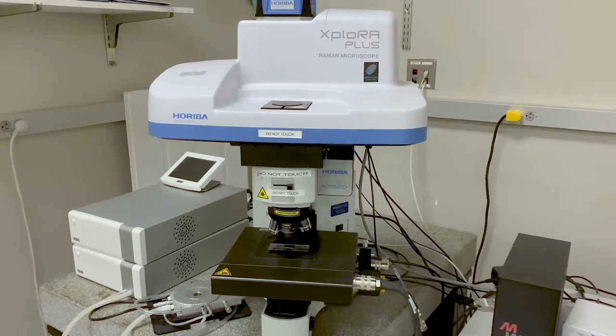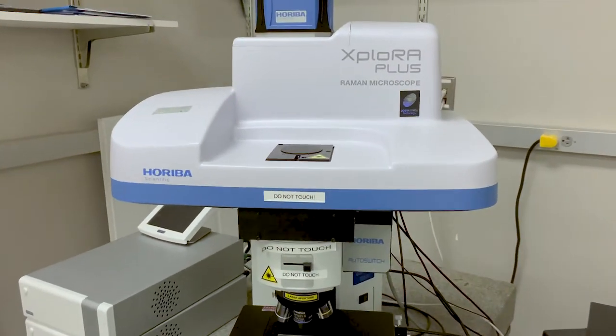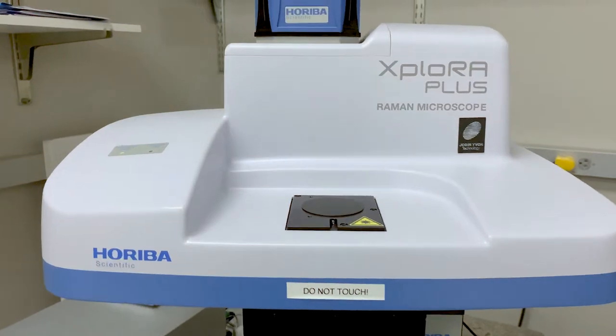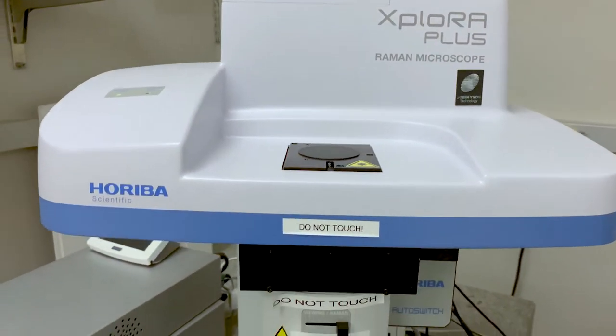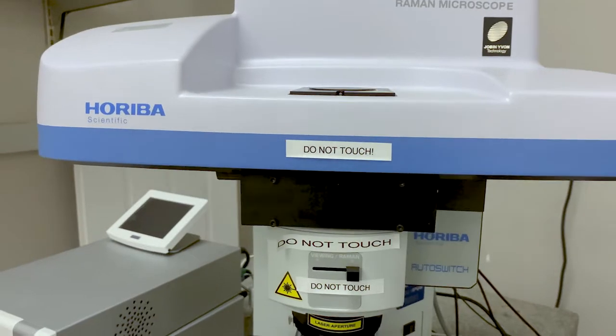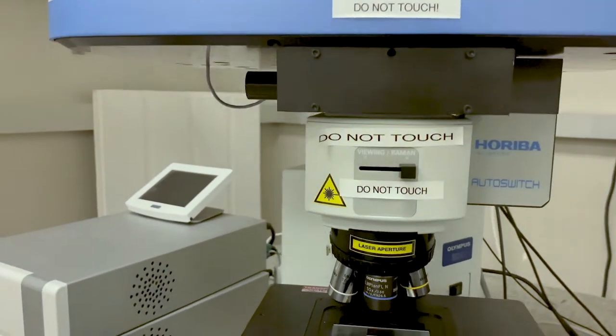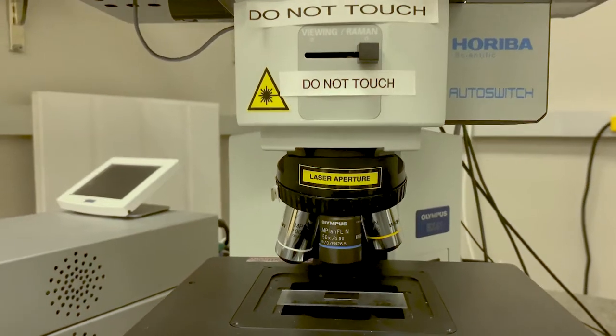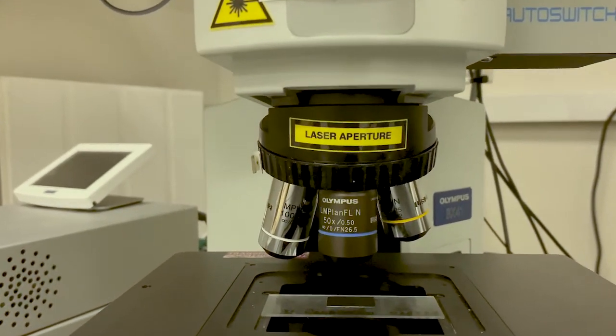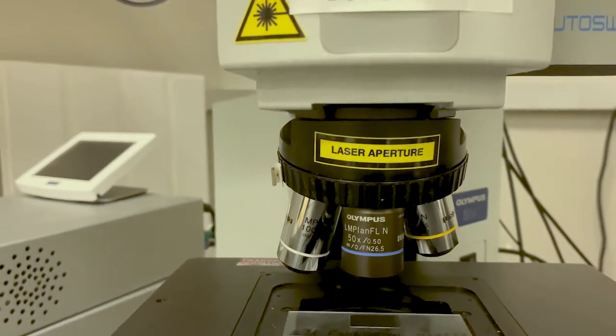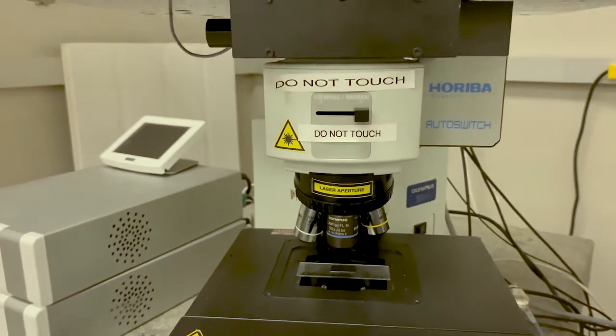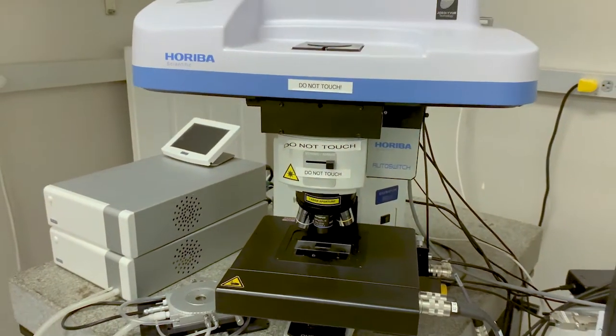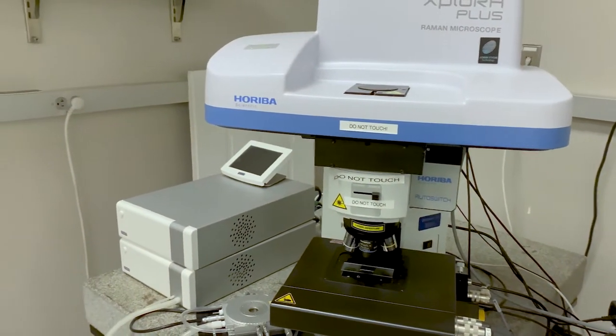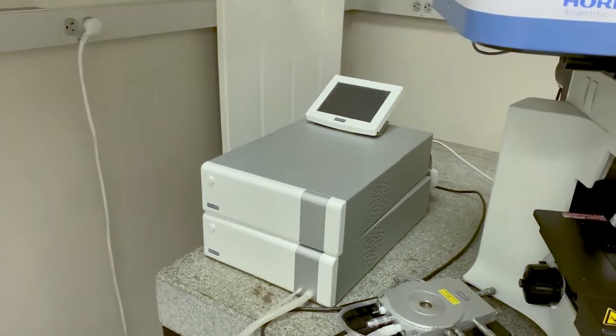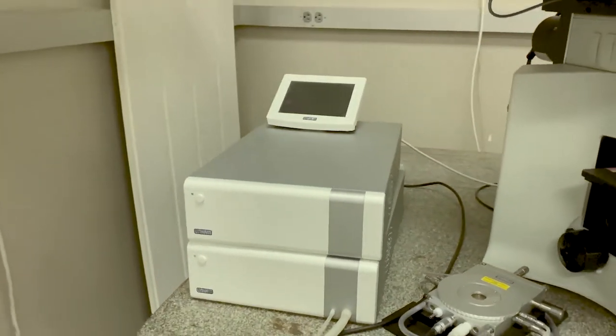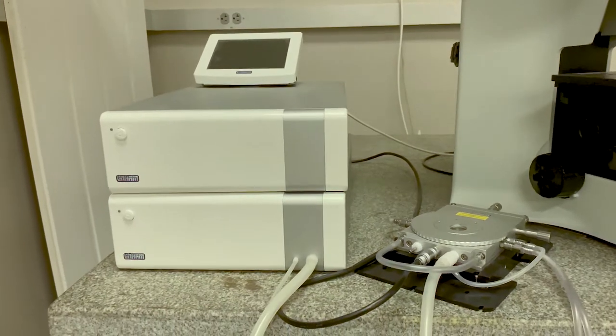This Horiba confocal Raman microscope comes with an integrated laser system with 532 nanometer and 785 nanometer laser wavelength. This microscope combines Raman spectrum and optical microscope, providing sample identification and chemical imaging on a microscopic scale. The Raman hosts a variable temperature stage with a range from negative 196 degrees C up to 600 degrees C.